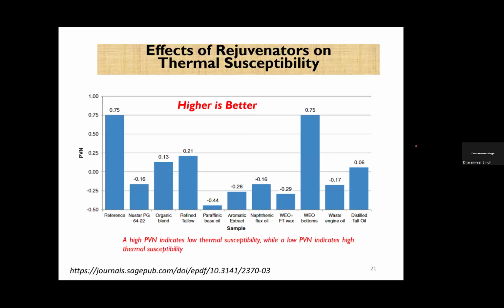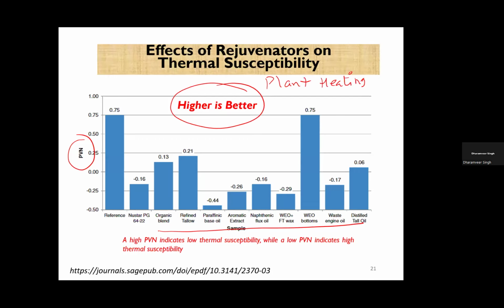Now, this is another very interesting finding. You have different kinds of rejuvenators, and the higher the value, the better. It means, when you add the rejuvenator in the plant, what happens? There is a lot of heating during production and then transportation. Quite possibly your mix may become highly aged within no period of time. So you want to make sure that whatever rejuvenator you use does not have an adverse impact on the performance of the mix. Higher the value, better is the mix. But if you see this kind of rejuvenator, they are creating certain problems in the mix.